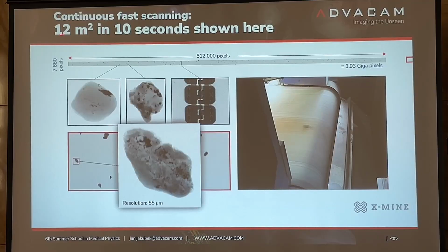So this thing, what you have seen, this scan is taken from a continuous stream. It was 10 seconds, and during these 10 seconds we have seen 12 square meters scanned with a resolution of 55 microns. You see that the whole image is roughly 500,000 pixels by 8,000 pixels during these 10 seconds, but it runs continuously. And the speed of the belt is in this case 2 meters per second.